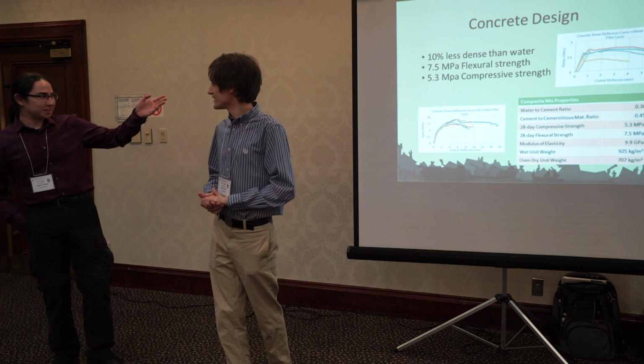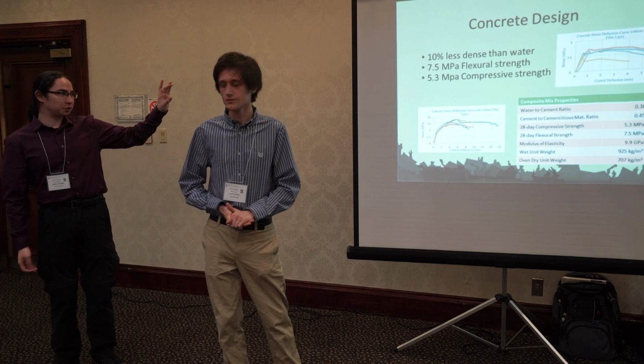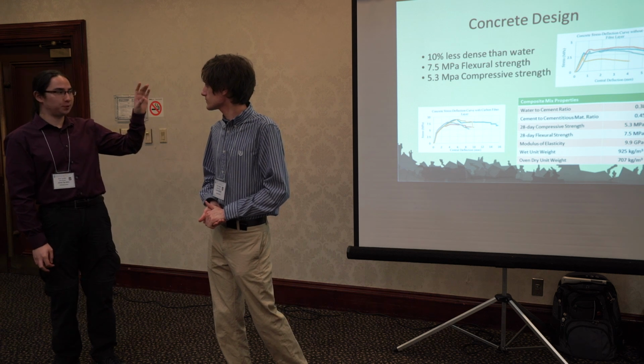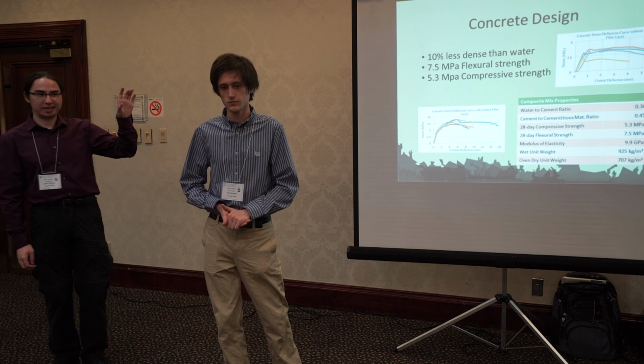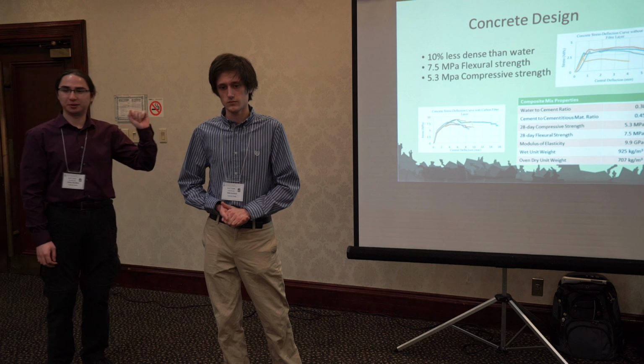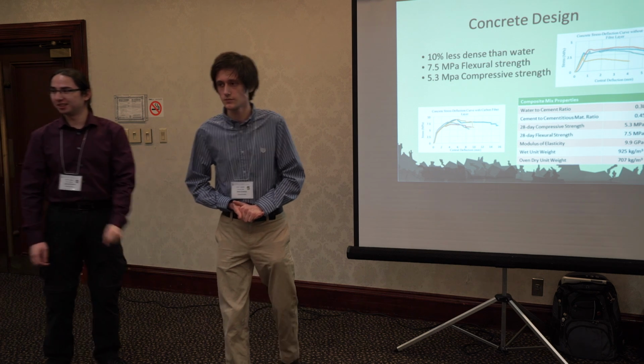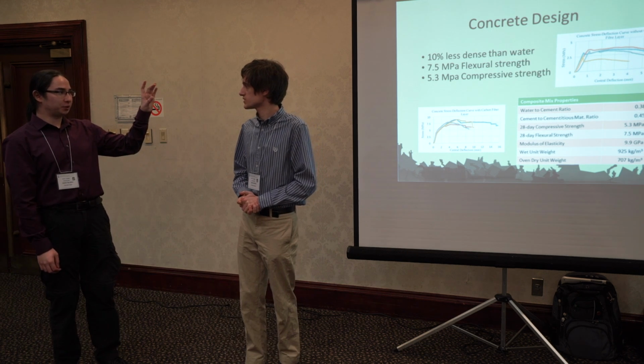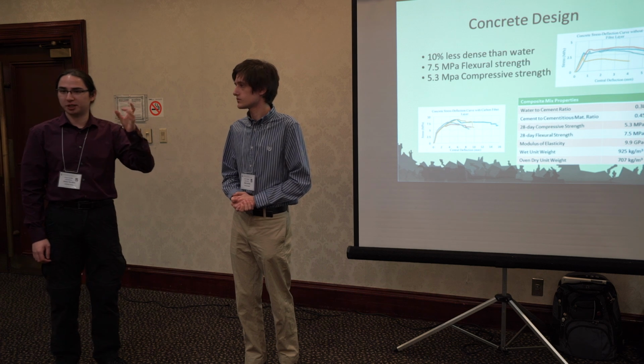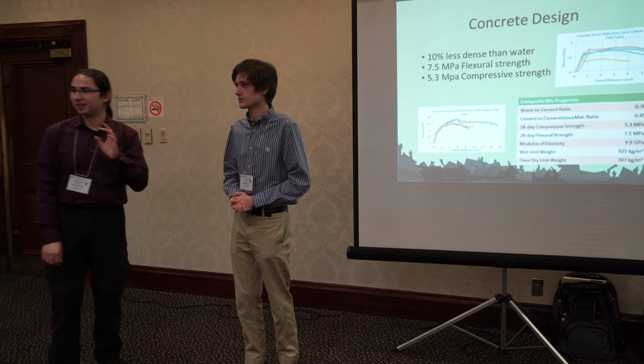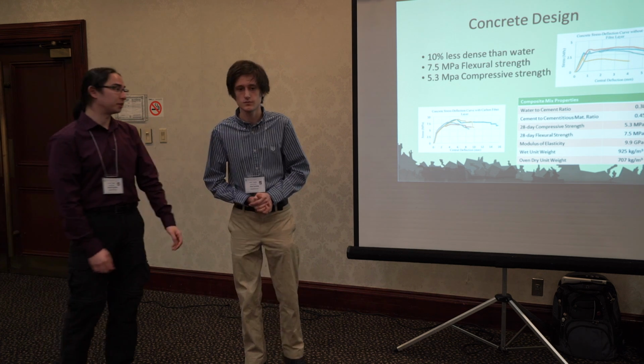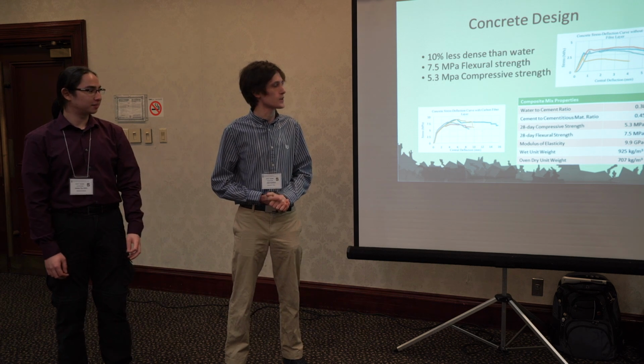Actually, a curious thing that comes out of our flexural and compressive strength is that our material properties are closer to that of a dense wood than they are to concrete, which I always find interesting. So essentially, both compressive and flexural strength ratio is more akin to that of a Douglas fir than any concrete you would find out in the industry.